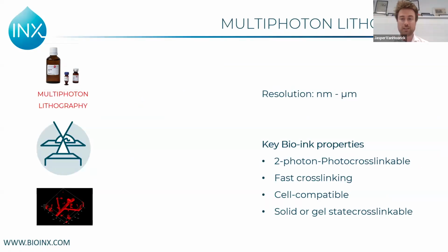So if we then look at the bio-ink properties there, the resolution you can achieve is hundreds of nanometers to micrometers. What's important here, your material needs to be 2-photon active. It needs to cross-link fast because it's very high resolution, meaning it is in a way the fastest printing technology, because your laser can be moved at meters per second or even hundreds of meters per second. But of course, resolution is extremely high, meaning that you need a fast chemical reaction, a fast cross-linking reaction, because if you have this high resolution, if you want to print something bigger, it needs to go fast.